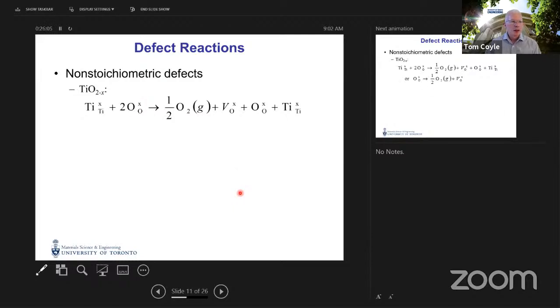Right. Now, TiO2. We're getting back to that automobile oxygen sensor, slowly but somewhat surely. TiO2 tends to lose oxygen to the surroundings, particularly when the oxygen content of the surrounding atmosphere is low. And so TiO2 loses oxygen to the atmosphere, represented in this reaction equation by the formation of half an oxygen molecule in the gas phase, leaving behind a vacancy on an oxygen site in the TiO2 crystal structure.